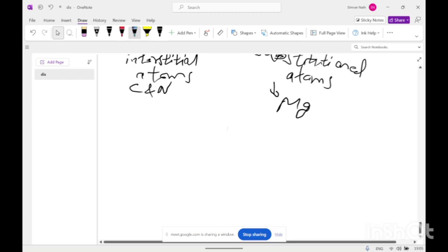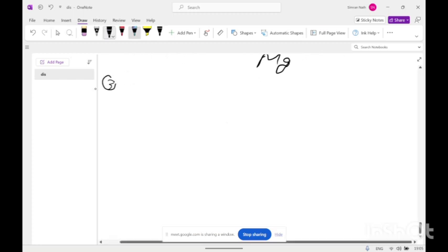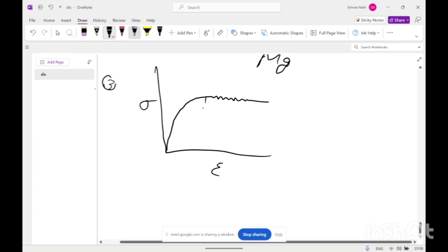And there is also a critical strain defined for a serrated flow to occur. Like if we draw a sigma versus epsilon graph, so the serrated flow always happens after a certain strain. So this strain is called the critical strain. The effect of temperature is that with increase in temperature, the critical strain required for serration decreases.